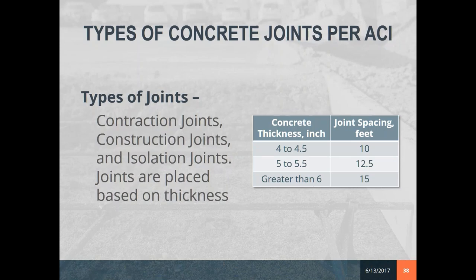There are contraction joints, construction joints, isolation joints. Again, the codes have very specific guidelines on the use of these and their placement. It's based on the different thicknesses of your concrete section. They really recommend having some type of control joint no further apart than about 15 feet. I know in my career, a lot of contractors try to push this to 20 feet with no interim control joint in between. You get the random cracking, and then it becomes a big issue later on the job site.